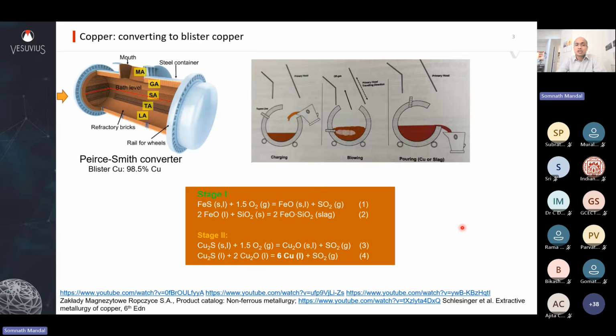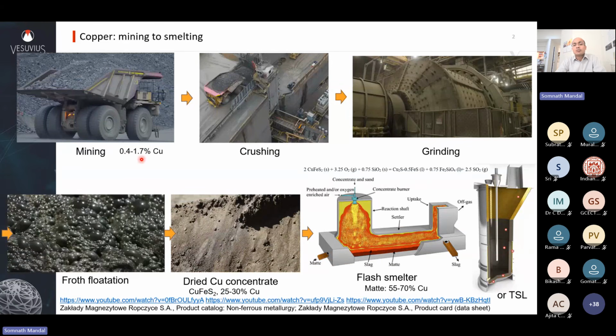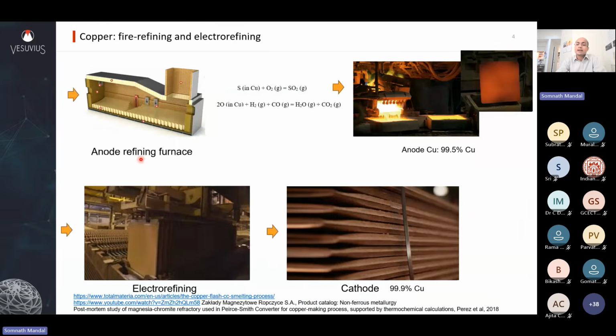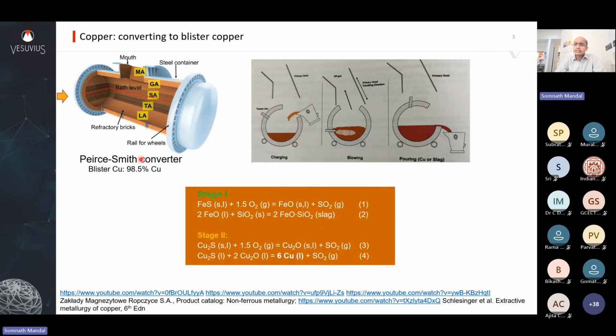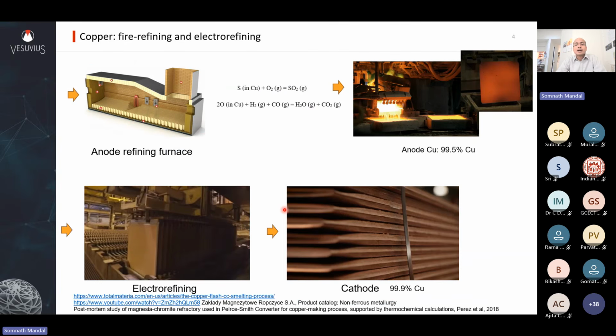You see, it's a big journey from almost 0.5 to 1% copper all the way to 99.9% copper. And the other thing is that the slag here is iron silicate, very acidic slag. That makes this process very challenging for refractories. You're looking at operation temperature somewhere from 1150 to 1350, depending on plant to plant and stages of the process. But this is a very harsh environment despite the lower temperature.